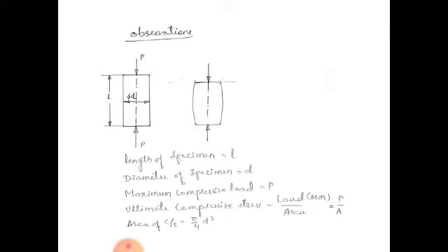Since the top and bottom faces of specimens are parallel, it is very difficult to ensure axial loading on the specimen. Since the length of the specimen is kept short, twice the diameter, to avoid buckling, within elastic limit a small compression takes place, which is difficult to measure. The friction between the ends of the specimen and clutches of the machine prevents the dimensions of the specimen ends from increasing.